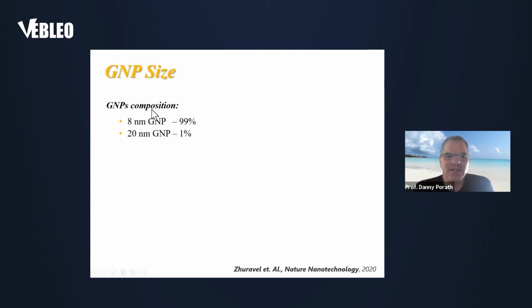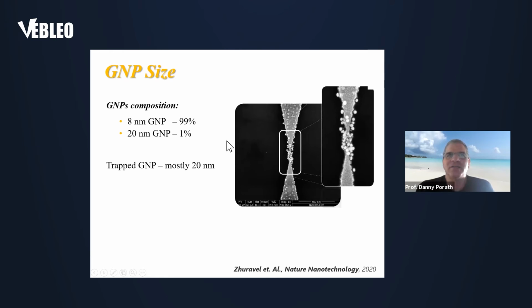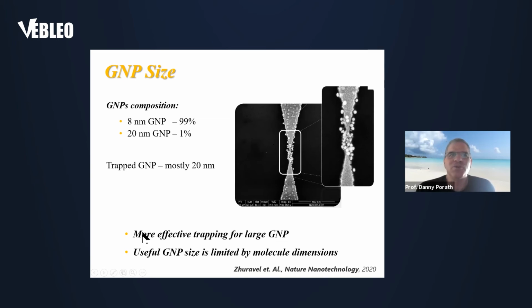So when we test the effect of the size of the nanoparticle, we took a solution in which 99% are 8 nanometer nanoparticles. GNP stands for gold nanoparticle, and 1% are 20 nanometer particles. And after applying the voltage, we can see that most of the trapped particles are the 20 nanometer particles. So in this sense, the larger the particle, the easier it is to trap in between the electrodes. But we want to have a matching between the size of the particle and the DNA, so we chose to work with 8 nanometer particles.